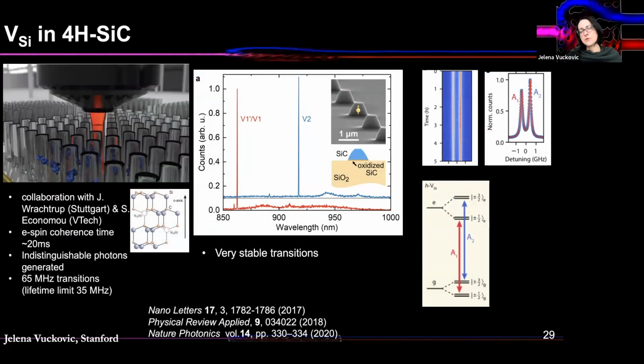And apart from diamond, as I mentioned, we also work with the silicon carbide color centers, and in silicon carbide, we primarily worked with the silicon vacancy, which is produced by kicking out silicon atoms from the 4H silicon carbide lattice by irradiation with electrons or ions. And here we've been collaborating a lot with the group of Jörg Wrachtrup in Stuttgart, which has done pioneering experiments on this particular material, and also Sophia Economou on the theory side from Virginia Tech.